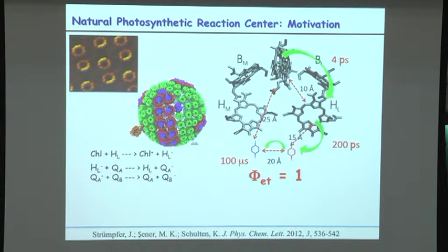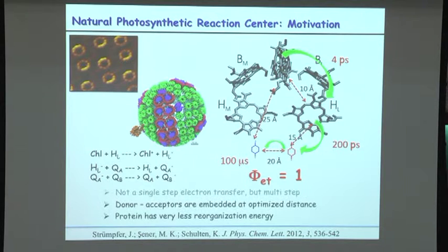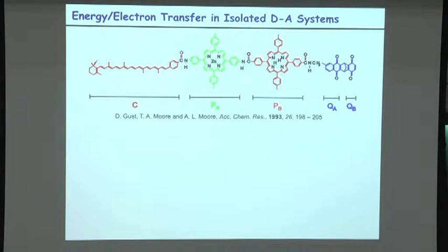That creates a barrier for forward electron transfer, but you can provide excess energy to have the forward electron transfer. It creates a barrier for the recombination, which is exactly what you require. We want to avoid recombination, and you can have ultra-fast charge separation because it is a connected system, and also you can have the injection by providing the excess energy. But once that has happened, you can clearly see that the stacks allow the charges to propagate. So we thought, why can't we mimic these kinds of systems?